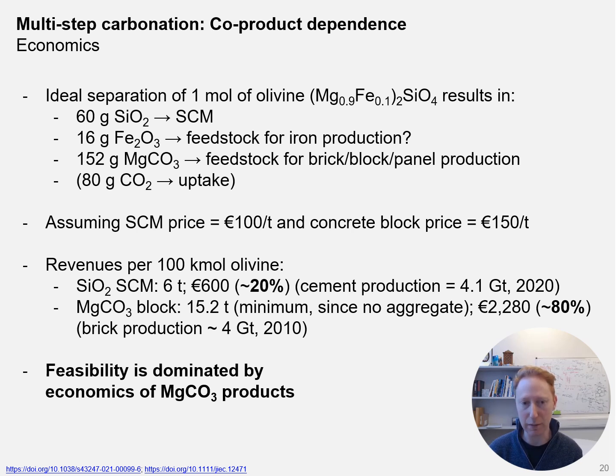It will thus eventually be priced similarly to those materials. So let's assume that we can sell the silica-rich supplementary cementitious material for around €100 a tonne, and that we can sell the magnesium carbonate blocks at the same price as concrete products, because that's what they would compete against, for about €150 per tonne.